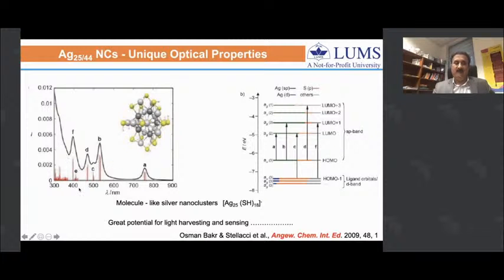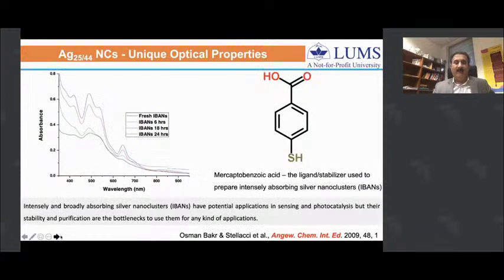In fact, they were able to prepare these silver nanoclusters using mercaptobenzoic acid as a ligand, and you can see that they were right, that it absorbed a major portion of sunlight. But unfortunately, they were not very stable. They lost their optical properties within 24 hours.